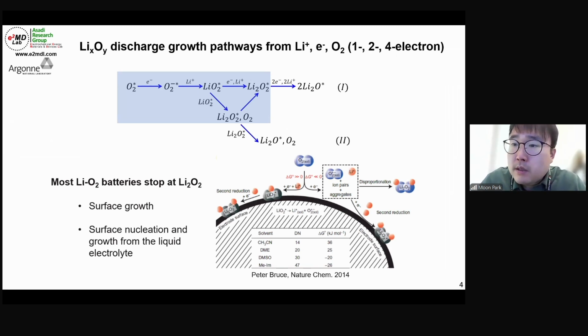This slide shows a typical discharge product formation process. You can see in the title, 1 to 4 electrons, which means there could be a 1-electron reaction, a 2-electron reaction, or a 4-electron reaction, and each one produces a different discharge product. The first is lithium superoxide through the 1-electron reaction. The 2-electron reaction forms lithium peroxide, Li2O2. And the last step is the 4-electron reaction forming lithium oxide, Li2O.